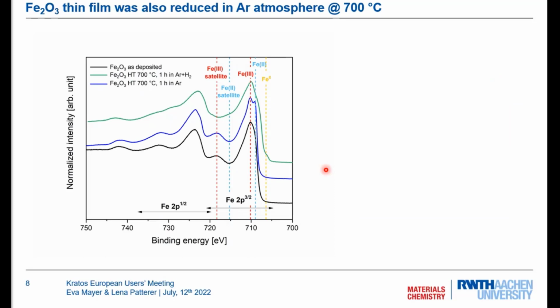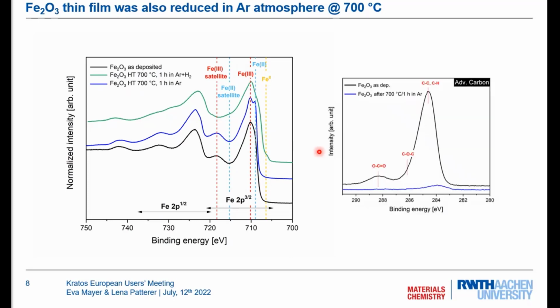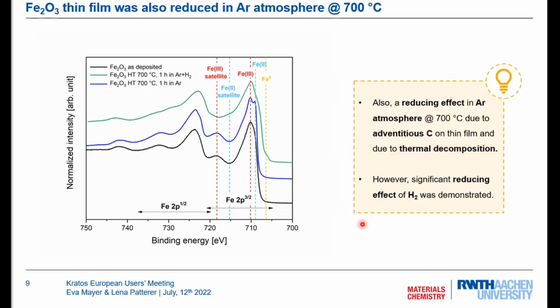And as a reference, we have conducted the same experiment in just argon to see whether there are other effects influencing the experiment. And here is a small shoulder for the iron 2 oxidation state, meaning that we have a little bit of reduction. This could have many explanations, for example, thermal decomposition, or also due to adventitious carbon. As you can see here in the carbon peak, which has been reduced in its intensity quite a lot. So carbon might have had a reducing effect on the iron oxide thin film.